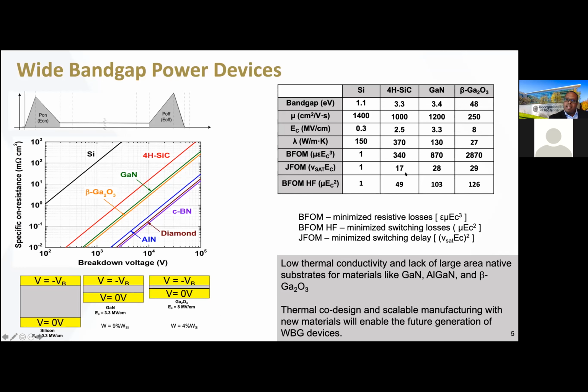If you look at this graph right here, we normalize everything to silicon. Silicon's 1. You can see as we go to silicon carbide, GaN, to beta gallium oxide, how the Baliga figure of merit increases. And you can also see how the Johnson figure of merit increases, as well as the high frequency Baliga figure of merit. So all of these figures of merit point towards the fact that going to higher bandgap or wider bandgap materials should give you some advantages.